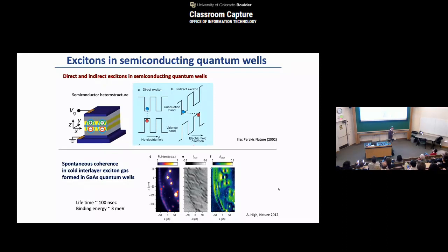Furthermore, because it's a semiconductor, although there are Coulomb interactions, all the dielectric screening of the semiconductor in three-dimensional structures makes this binding energy relatively weak, about 3 millielectronvolts. So this can only be done at relatively low temperatures and is rather feeble. You cannot create too high a density, otherwise it starts unbinding. But this gives us enough of a hint of the directions that we can move.